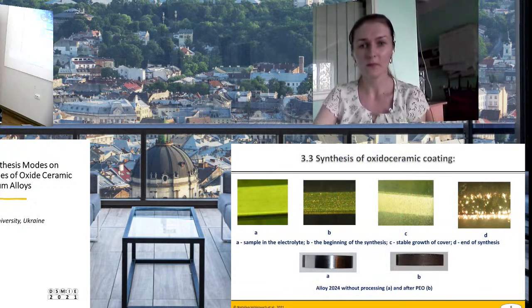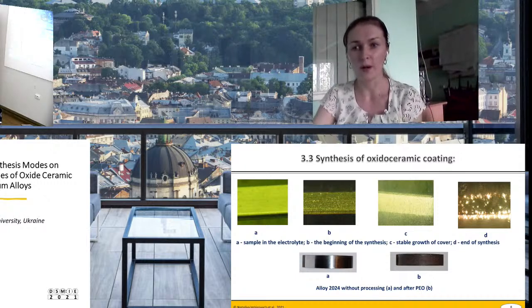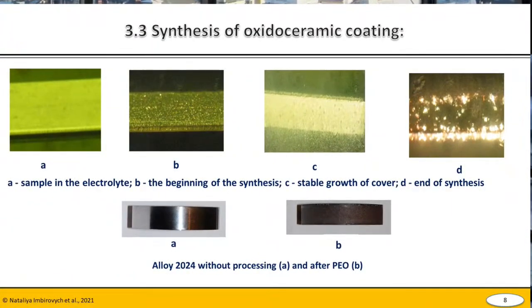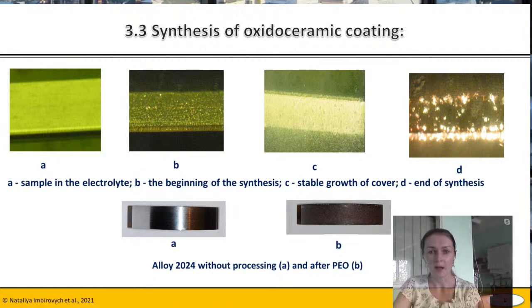Thank you. In the synthesis of oxide ceramic coatings, the stage of formation of spark discharges on the surface of the sample is very important. Plasma is formed within 3 to 5 minutes. The voltage in this area increases. You may see it on drawing B. As the coating thickness increases, the voltage at the anode gradually decreases.